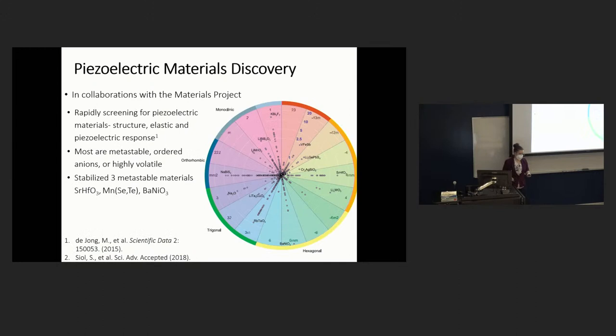My background and my specialty is in piezoelectric and ferroelectric materials. I've worked a lot on discovering new piezoelectric materials because it's very difficult to determine if something's going to be ferroelectric or multiferroic. It's very difficult to predict that. So we start searching first with piezoelectric materials, right? This is work that was done in collaboration with the Materials Project. They came up with a list of interesting, potentially high piezoelectric response materials, and that's what's shown here on this graph. It's just a dot for each one, radially showing its e_ij piezoelectric coefficient.